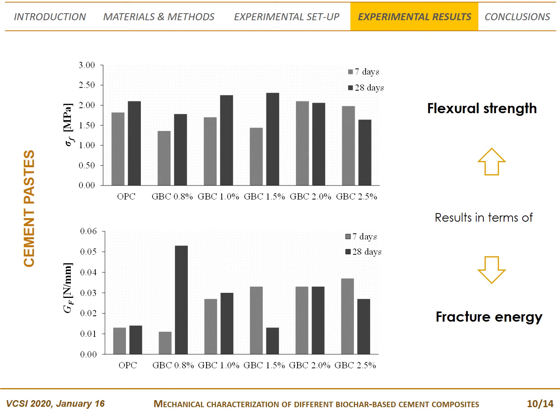The highest percentages of biochar addition lead to an increase of flexural strength at 7 days, while the results at 28 days are profoundly different between the two batches. The specimen with 2% addition shows about the same flexural strength as the reference, while for 2.5% a significant decrease can be observed, probably due to a non-optimal dispersion of biochar in the cementitious matrix. The results of fracture energy at 7 and 28 days do not follow the same trend of the bending strength. Results at 7 days show an increasing trend, while the results at 28 days are difficult to interpret because of fluctuations in values that could be explained by the ability of biochar to interact with the hydration of the samples during the curing phase.